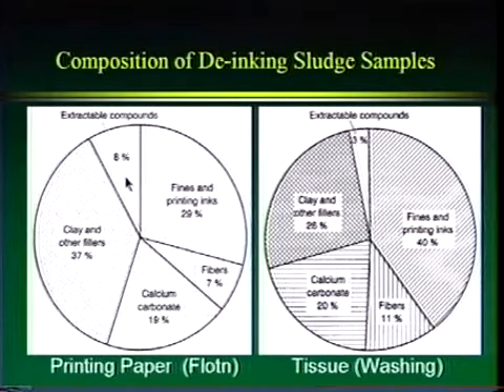So we're getting rid of a lot of the filler, and 8% is extractable compounds like pitch, stearic acid, flotation aids, things like that. Now, if we compare that with a tissue making process that's going to use washing, why is it going to use washing? Again, because we want to get rid of as much filler, inorganic material as possible, and washing will allow that filler to fall through the washing wire and come out, and that will protect our creping blade. If you look here, now we've got 26 and 20% of the inorganic filler, so we're getting large amounts of this inorganic material in our sludge. We're getting some fines and printing inks coming out from the washing, and we're getting some fibers, about 11%, and also some extractable compounds.